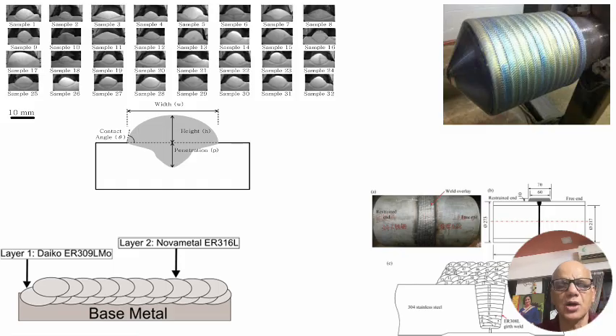We can also do ultrasound to see the bond fusion, because DP will give you only the surface defects. Ultrasound will give you if there is good bonding, if there are any side wall fusion issues, if there are any penetration issues in the number of layers which we are going to do. So every layer has to be thoroughly cleaned. If you have any doubt, grind it to white. Don't see any undercuts, and then do a DP, and once the DP is properly cleared and washed, then you can deposit weld material on top of it.